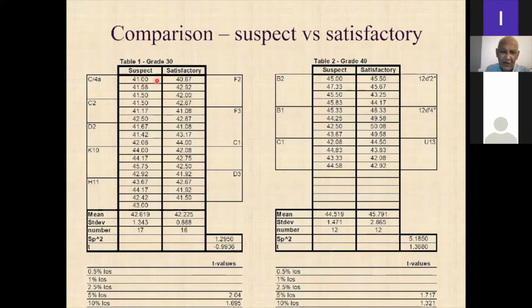So these are different locations where you have satisfactory concrete and different locations where you have suspect concrete. You don't actually need the same number of readings either, but you need typically about 15 to 20 readings. Maybe you can manage with about 12. It just depends on whether it makes sense statistically. Here you have fewer because there is less area with grade 40 concrete.